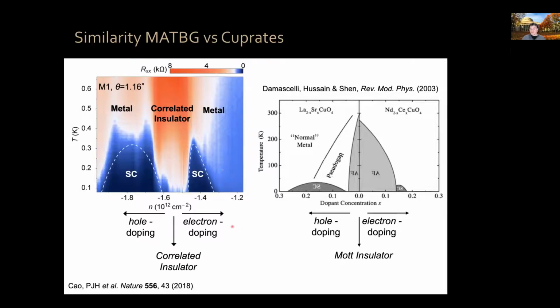A big difference, of course, is that this is a theoretical phase diagram. In order to realize it, you need to fabricate and grow hundreds and hundreds of crystals, one for each doping on this axis, and cool down many times and measure all of this data. In our case, however, we measure this continuously because we can vary the doping electronically by dialing a knob on a gate. And we can go from here to here just in a few seconds.